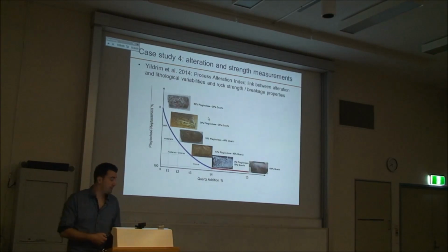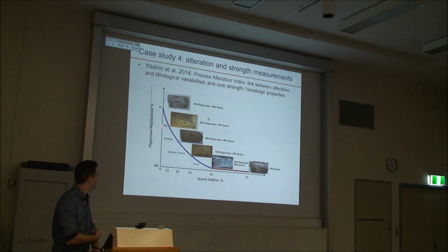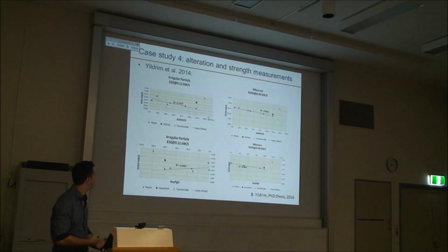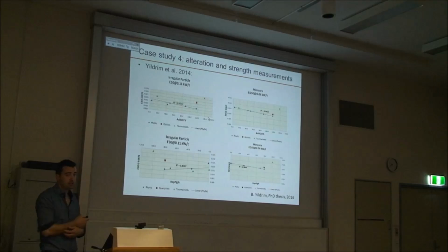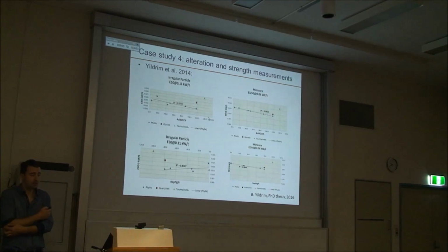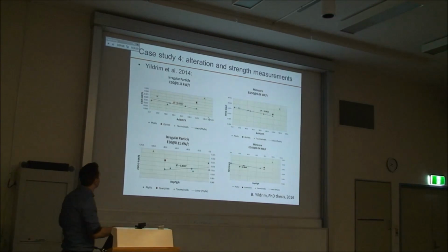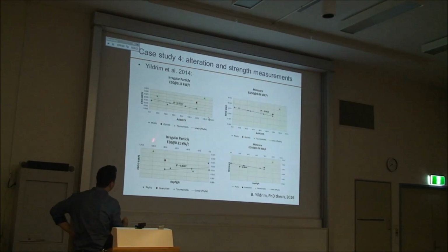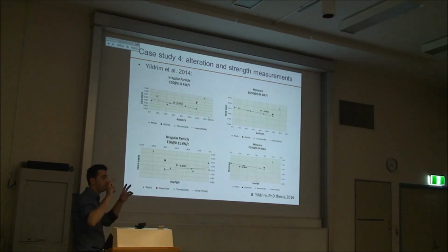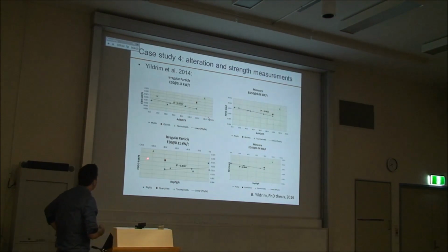So there's a paper on this that explains how they actually estimated the replacement of plagioclase and quartz by XRD. So I invite you to read that paper. So the results are shown here. On the left side, Barris did the test with the irregular shaped particles and looked at the E50 as a function of the addition of quartz or the replacement of plagioclase, like his process alteration index.